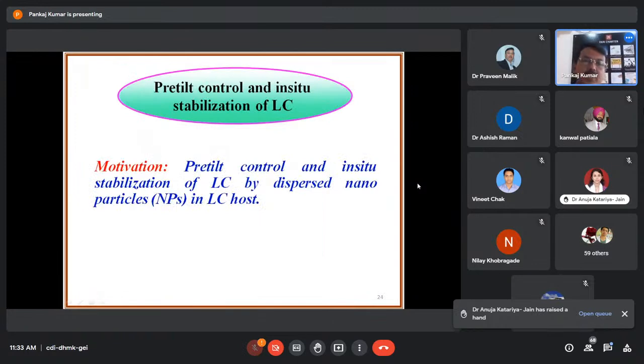Again, the second part of this presentation, or this work, is: if we want to make the response time faster, as well as reduce the threshold voltage or operating voltage, then pre-tilt control is one of the methods. So in that case, pre-tilt control and in situ stabilization of liquid crystal by dispersed nanoparticles are also performed in